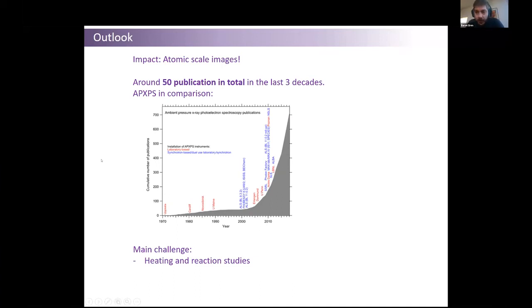And the main challenge of this technique, and it still is the main challenge, is really heating. The problem here is that if we heat our surface, because of conduction or because of convection of the gas phase molecules, we also start heating other parts of the microscope, especially the piezoelectric materials, and this induces some thermal instability, sometimes makes it really impossible to image.